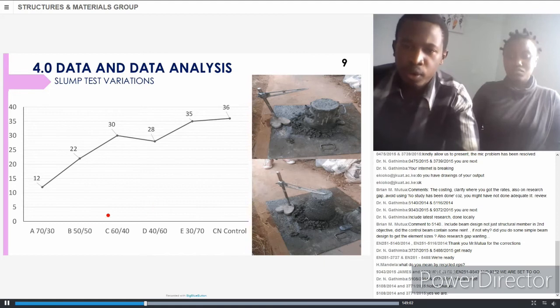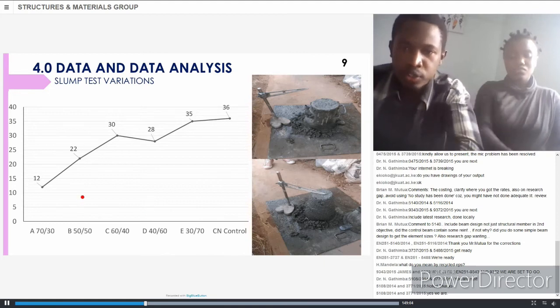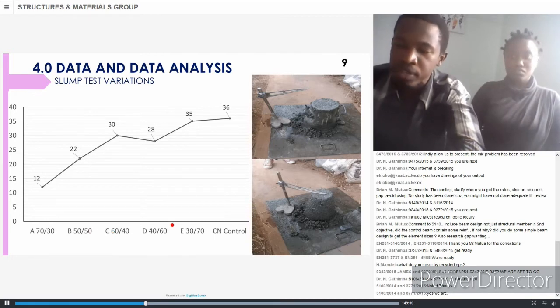The slump also showed variation with increase in proportions of plastic. The more workable mix was the one that had a higher plastic percentage, as you can see, 30% rubber and 70% plastic. And the least workable mix was the one that had the highest proportion of rubber content and the least amount of plastic.